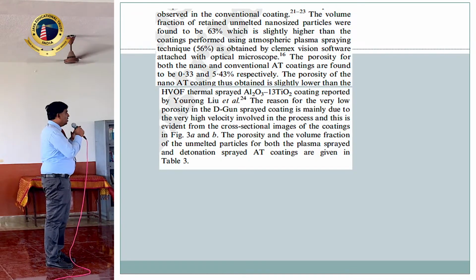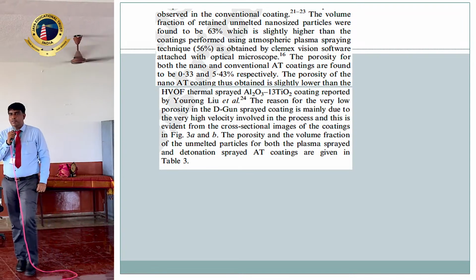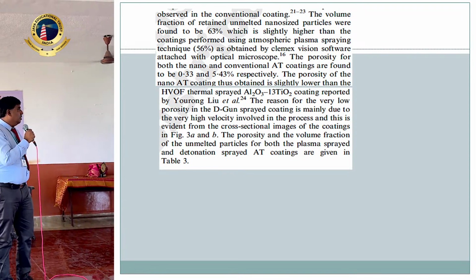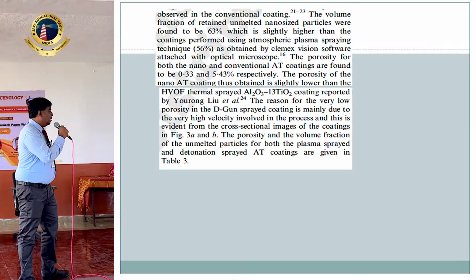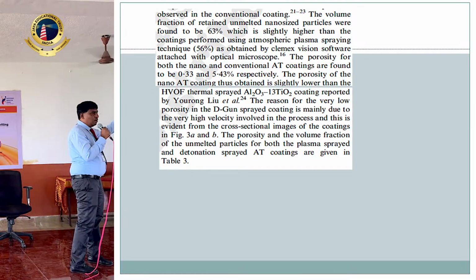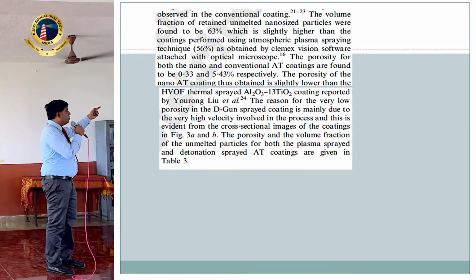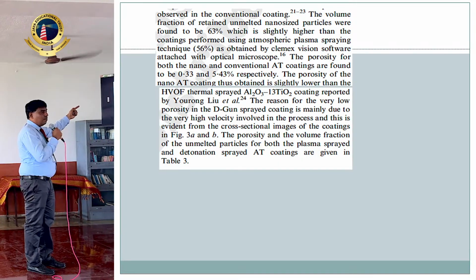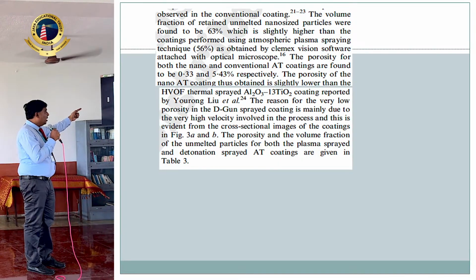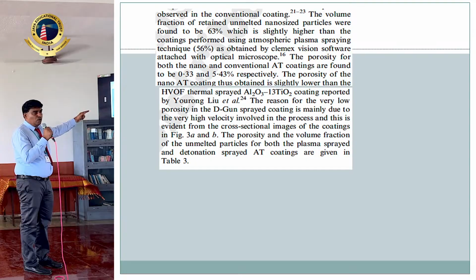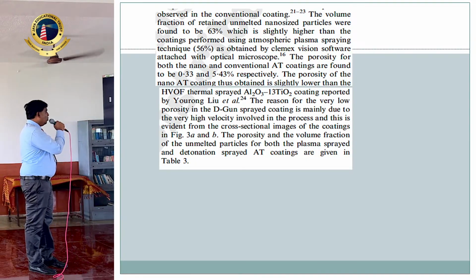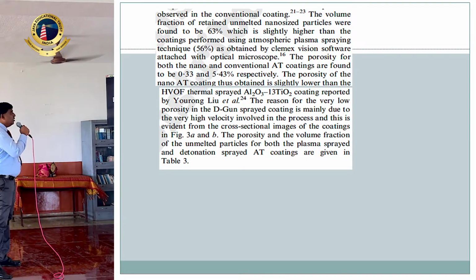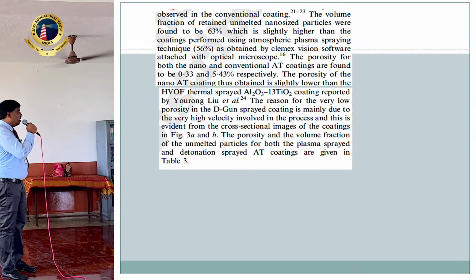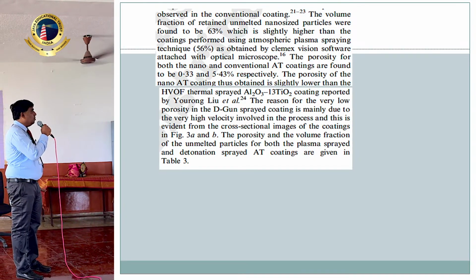Then I have specified the reason. Actually in my work I got very low porosity. So that is being compared with a researcher who performed HVOF thermal sprayed alumina titanium coating. That is reference number 24. Then I am justifying the reason why I got low porosity. The reason for the very low porosity in the detonation gun sprayed coating is mainly due to the high velocity involved in the process, and this is evident from the cross-sectional images of the coating.